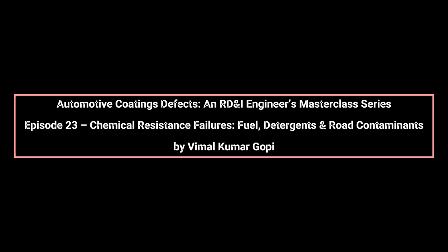Road contaminants introduce mixed attack modes. Brake fluid is hygroscopic and penetrates deeply, often causing blistering and staining. Road tar contains solvents that soften clear coat surfaces. Industrial fallout deposits acidic or metallic particles that react in the presence of moisture. Each contaminant stresses the coating differently, revealing weaknesses in different layers.